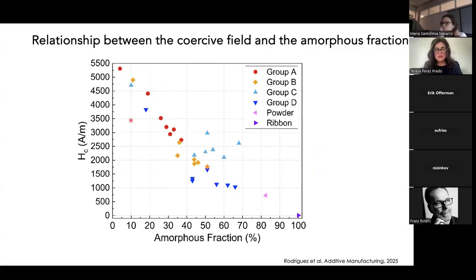For one thing, the coercive field varies with the amorphous fraction. The variation is more or less linear for fractions that are smaller than 50%, but after that, other factors come into play, which are maybe residual stresses, the size of the crystallites, and so on. This is something we didn't get into to decouple the influence of all these elements, but we could report that the variation of the coercive field with the amorphous fraction becomes more complex.